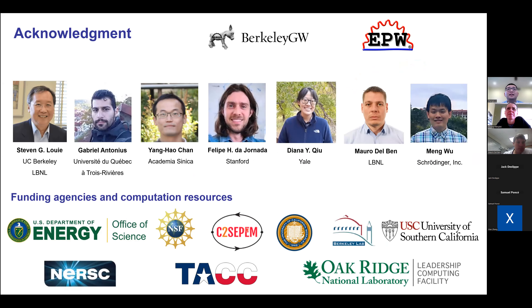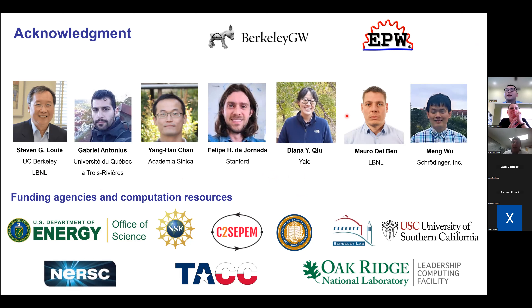To summarize the take-home messages: first, we developed GW perturbation theory (GWPT) for electron-phonon coupling, including correlation effects through the dσ/dR contribution to the matrix elements. Second, we developed a workflow combining Abinit, BerkeleyGW, and EPW for practical GWPT calculations. Third, through several examples we have shown that self-energy effects can largely renormalize electron-phonon coupling and should not be neglected in correlated materials.